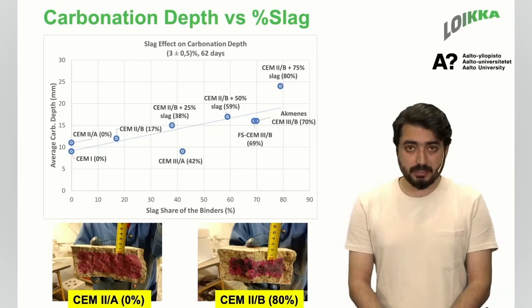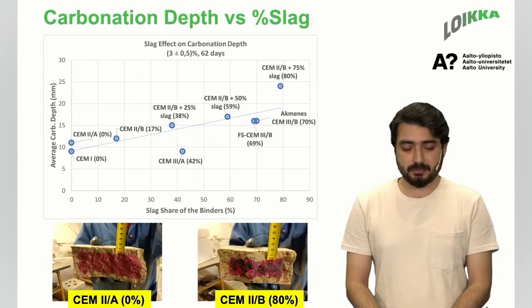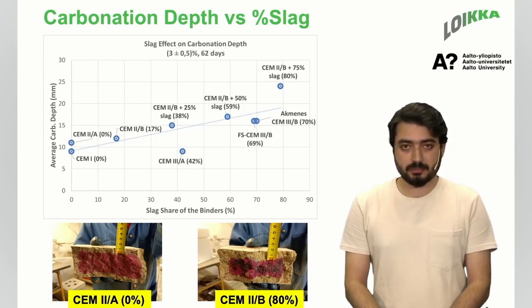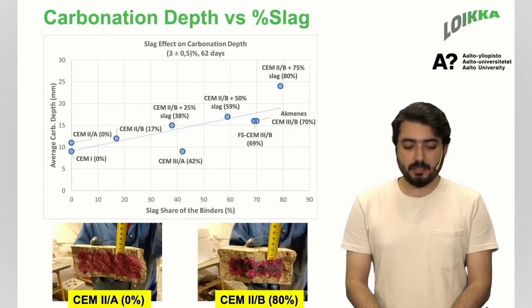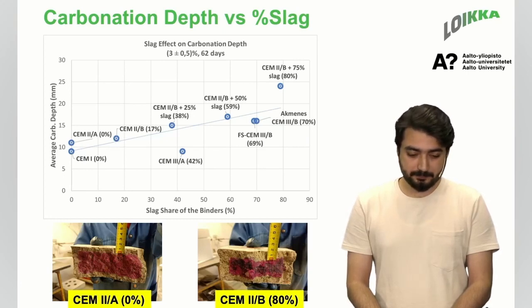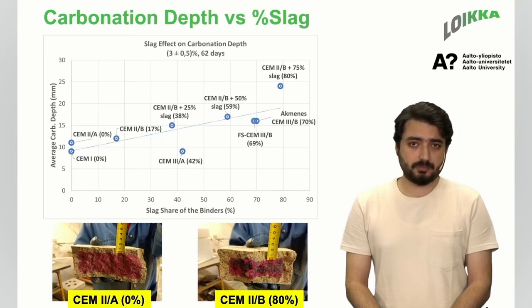Moving forward with carbonation depth and its correlation with slag. On the x-axis, we have the slag increase from 0 to 80%. If the slag content is increasing, so is the carbonation depth. The carbonation depth here is quite large, in reality 5 times or more than the actual case. The reason was the carbon dioxide concentration in the carbonation chamber, where we kept the samples for 62 days, approximately 2 months, and the concentration was 3 plus minus 0.5%. We did this because of a bit of a time constraint.